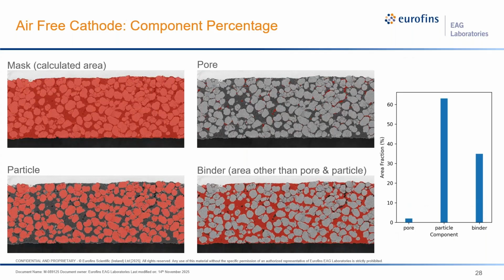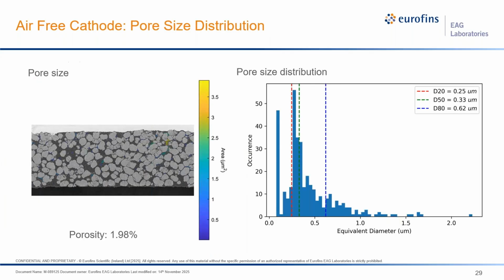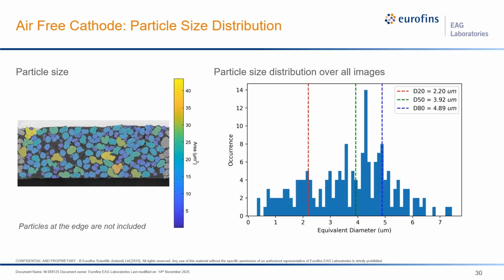In addition to this, we can collect cross-sectional images of the individual components, and afterwards, by image processing, we can look for the areal fraction of the pores, particles, or binders in between the particles. As you can see in this example, the particle component forms the majority of the image, which is above 60%. Then the binder is a little below 40%, and the rest is pore. More detailed analysis is possible. By looking into the pore size distribution, we can check whether they are uniformly distributed or not. We can also check the same thing for the particle size distribution.